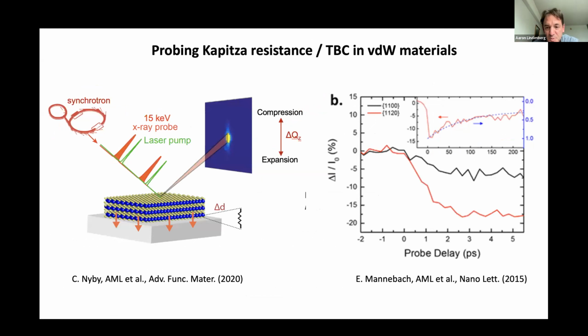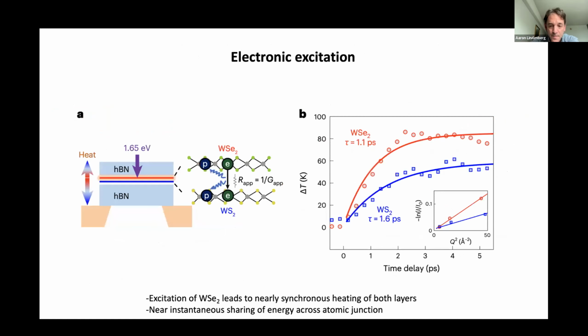Okay, I'll just briefly mention that we've done other measurements probing these types of TBCs using X-ray scattering in the monolayer. We can also do this by, for example, probing the relaxation of the energy as the system cools into the substrate. And the numbers one gets for these types of resistances are all essentially consistent to first order. Okay, so now here was the first big surprise in these experiments.